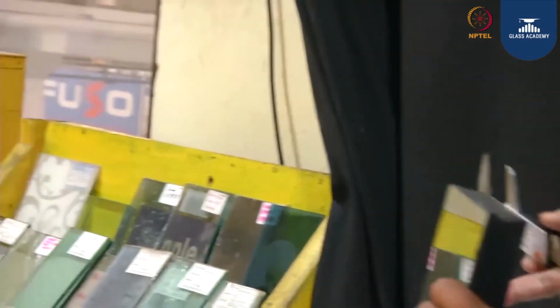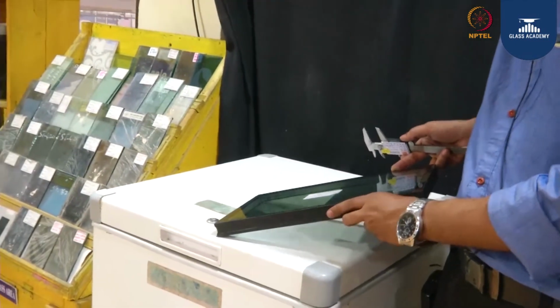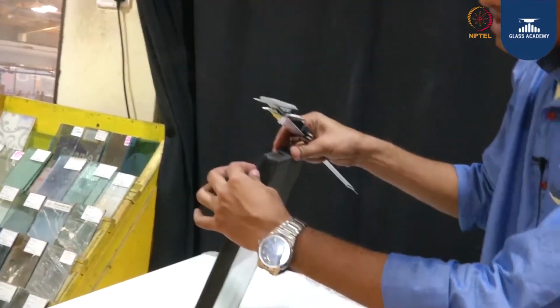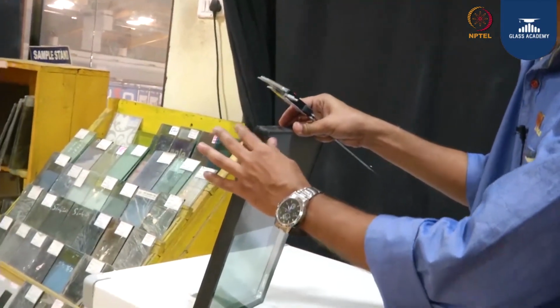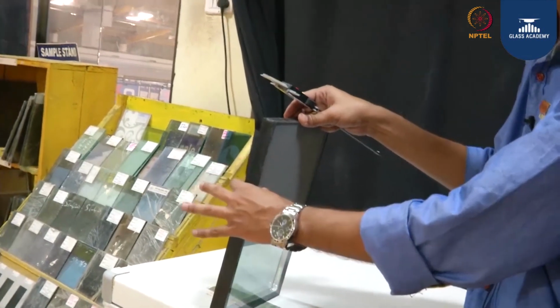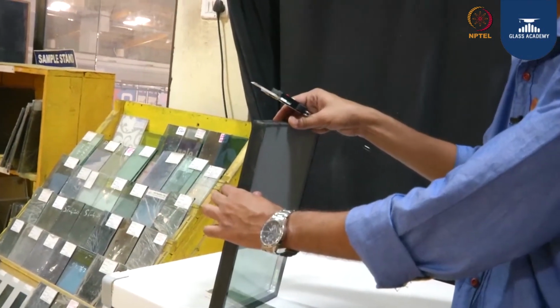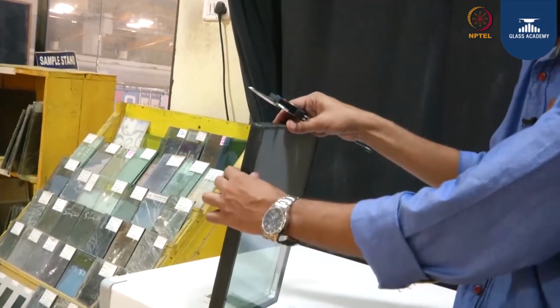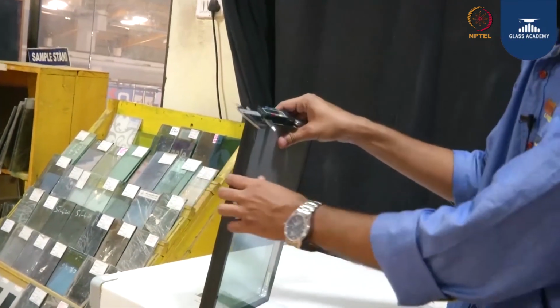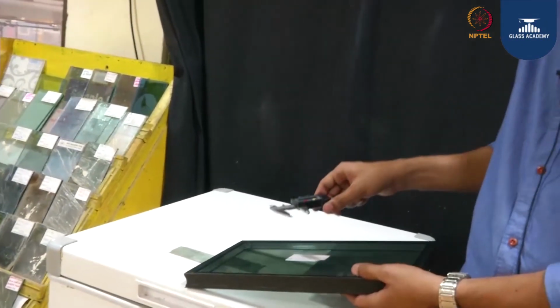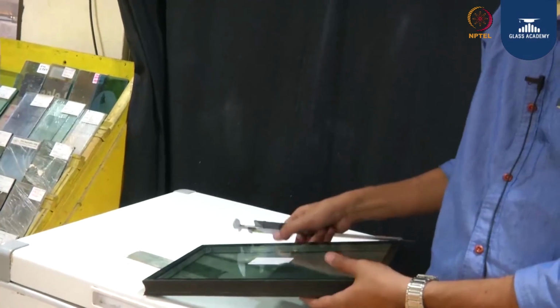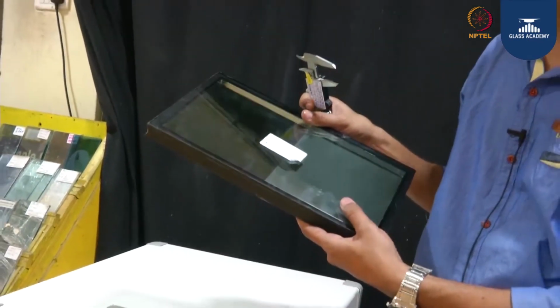So if you see, the average overall thickness is almost remaining the same. The glass combination is 6mm, 12mm, 6mm, so it should be 24mm, whereas we are getting 24.7 on an average. As per the standard, plus or minus 1.5mm is allowable. So through this test, we are assuring that the overall thickness of the DGU is maintained throughout the product.